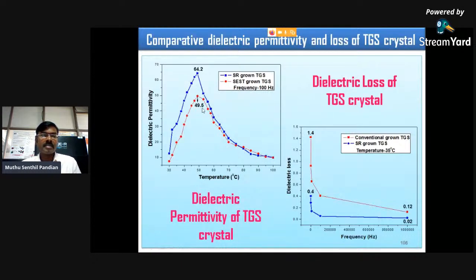This is a special material for crystal growth people. Almost all the people are working on it with the conventional method, SR method, and other solution growth methods also. The dielectric permittivity value for the SR grown crystal is 64.2, but in the case of the conventional method grown crystal it is 49.5. The higher dielectric permittivity and the lower dielectric loss in the case of the SR grown crystal clearly indicate that the crystalline perfection and optical quality of the SR grown crystal are higher compared to the conventional method grown crystal.